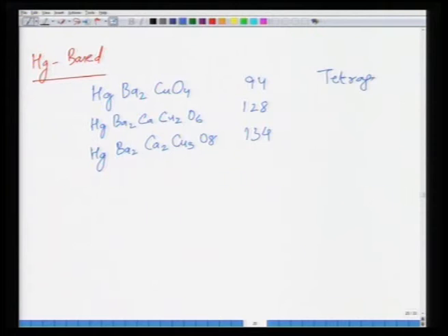all with tetragonal structure. So you can see that these cuprates which have layers of copper oxides, if you tune the composition by putting in a variety of atoms in the structure, you can change the Tc quite well. The problem with mercury and thallium based is that they are difficult to handle. They are poisonous, and many countries have banned or restricted their use. So as a result they didn't pick up too much, but still huge research was done on yttrium based cuprate